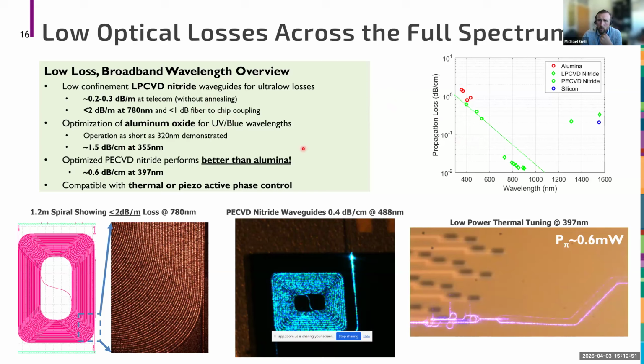But then moving into the shorter wavelengths, it becomes much more challenging. For blue wavelengths, we've developed aluminum oxide waveguides. That's these red points right here. We've been able to demonstrate very low losses on the order of 1 to 2 dB per centimeter, going down even as low as 355 nanometer wavelengths.